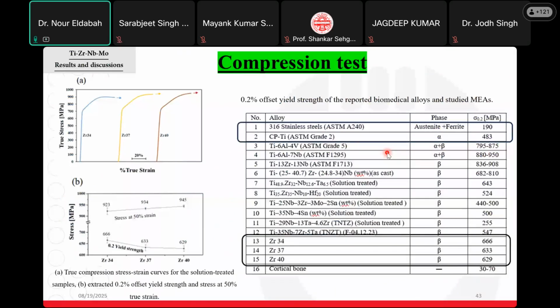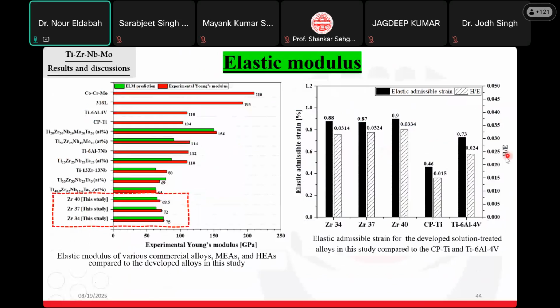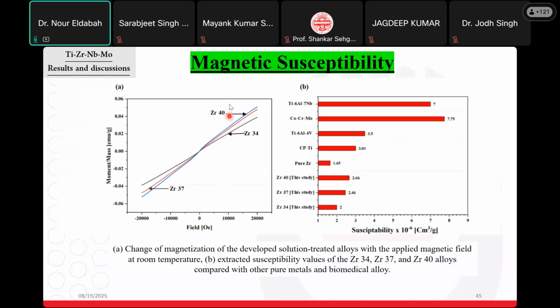Here also you can get an indication about the H over E, or the hardness over the elastic modulus value, and it is very high for the produced alloy, which gives an indication about the wear and abrasion resistance of the produced alloy. The magnetic susceptibility, when you make a linear fitting, shows no saturation behavior, so the alloys are paramagnetic alloys, with values lower than commercial pure titanium or titanium 64. So we have successfully achieved a low magnetic susceptibility.